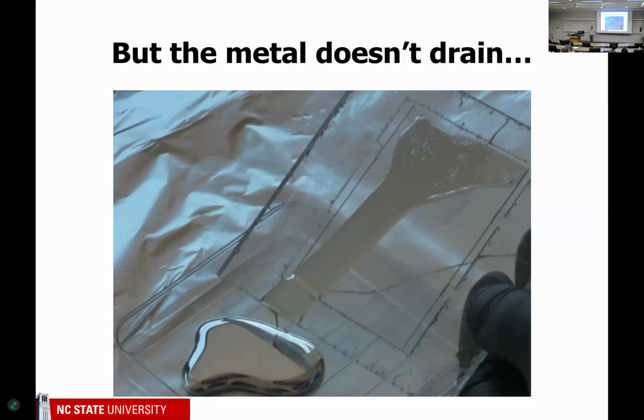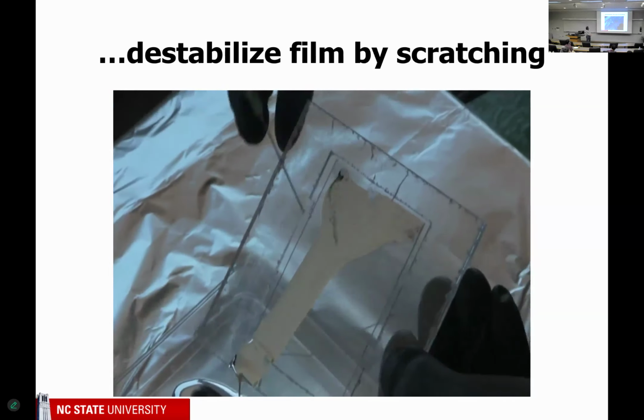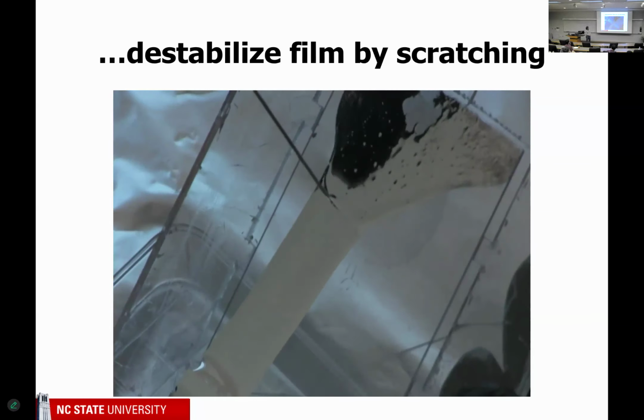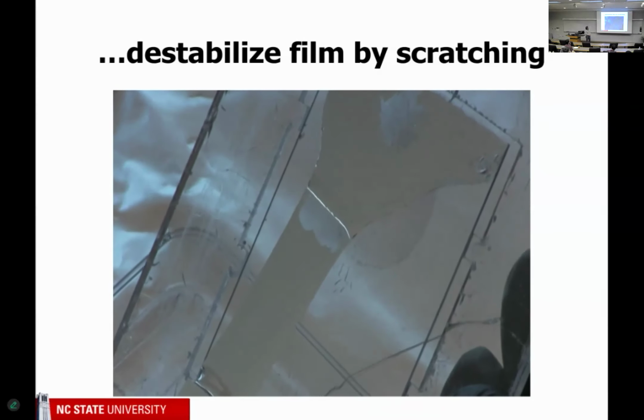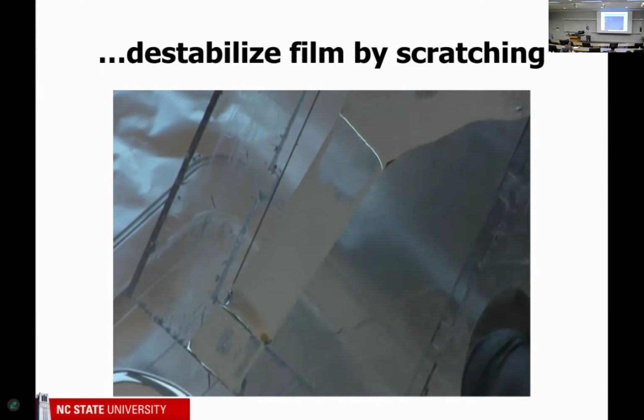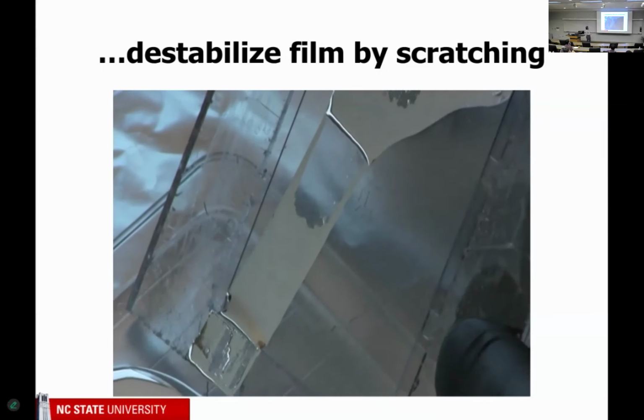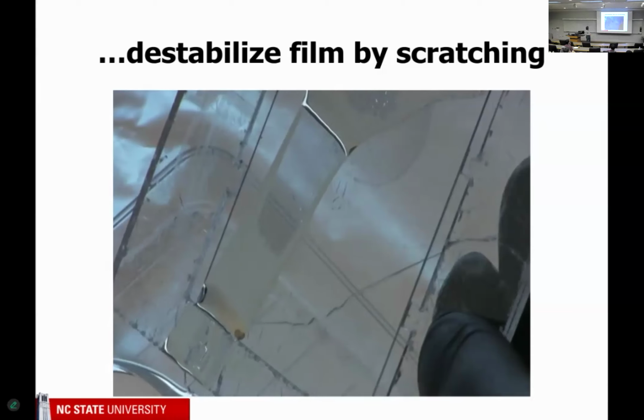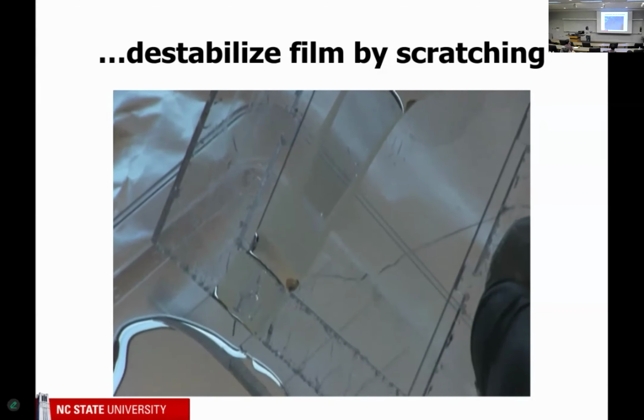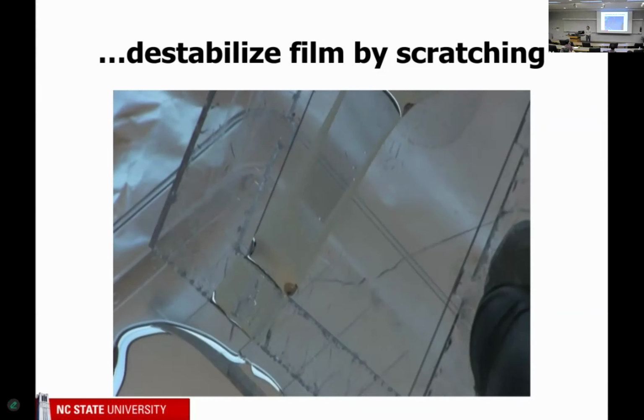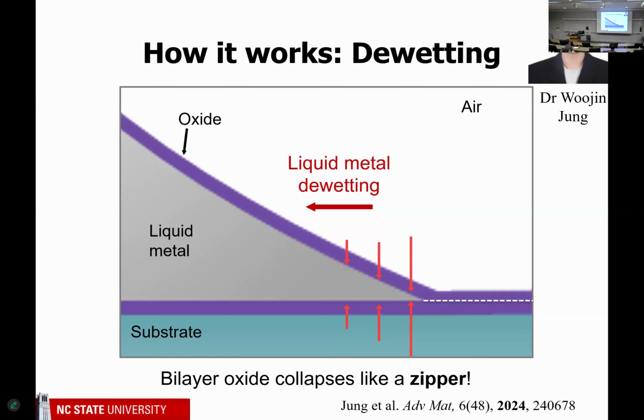So the popsicle analogy does not work. It's not easy just to remove the liquid. It tends to want to be inside of its own oxide. But it turns out, if you take that same film and you scratch it, you can actually destabilize this film, and indeed, the liquid will flow. Good reaction, thank you. I had the same reaction, I almost fell over. So the liquid drains, and what's left behind is just the oxide. Okay, and so that's one way to do it, but it's not the best way.